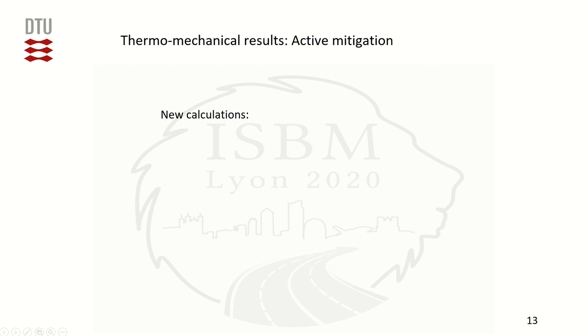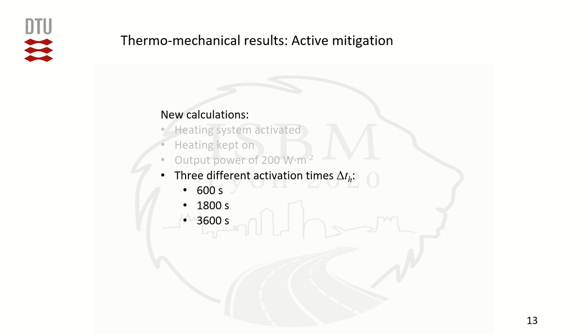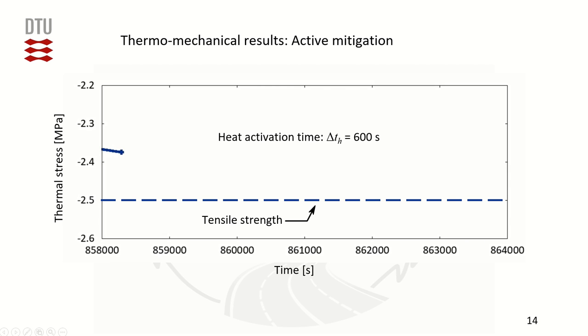Next, thermomechanical calculations were repeated, this time with the heating system being activated prior to the aforeidentified cracking event. Once the heating was activated, it was kept on, with an output power of 200 watts per square meter. 3 required times of heating system activation were investigated: 600 seconds, 1800 seconds, and 3600 seconds. The presented chart offers a magnified view of the thermal stress for the last 6,000 seconds of the simulation for an activation timing of 600 seconds. As can be observed, the heating was not activated early enough to mitigate the cracking event, as the thermally induced stress reaches the half-space material tensile strength.